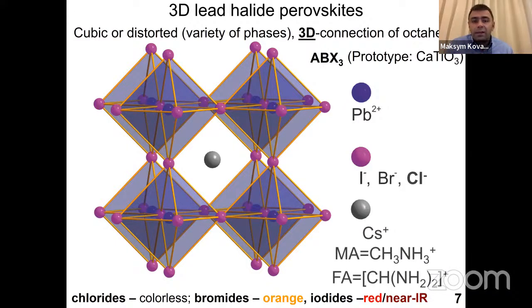semiconductors known as lead halide perovskites have been rediscovered as optoelectronic materials. Initially in the semiconductor solar cell as a semiconductive absorber for solar cells. So just to briefly introduce, they are called perovskites because they have exactly the same crystal structure as oxides, which have perovskite crystal lattice, such as calcium titanate, but they are not made of those elements. They are made of lead and halide. So the valences here are a factor of two smaller than these, but the crystal structure is the same. So that's why they are called lead halide perovskites.